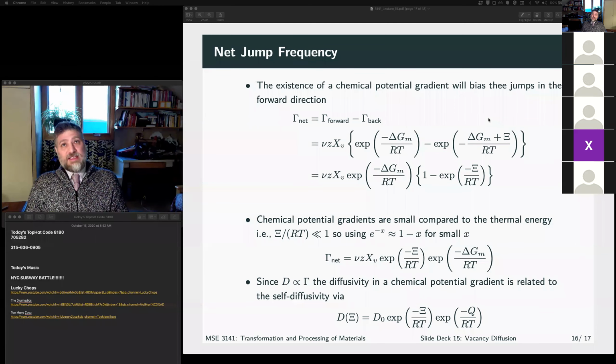There's an effect that's not really understood very well in my primary area of plastic deformation: if you pass an electric current through hexagonal metals in particular, you get an alteration of the flow stress that's different than if you just heated it up to the temperature, right?